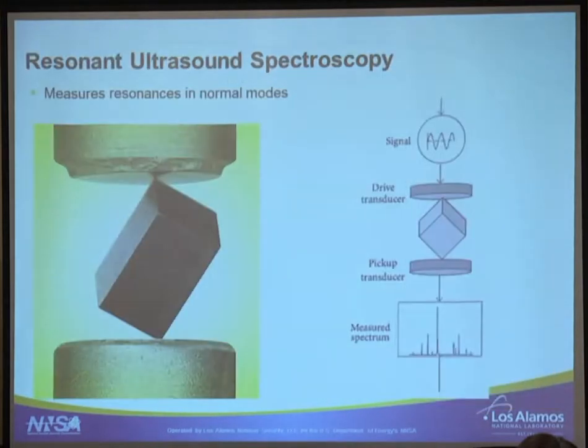I know. Anyway, so the basic technique is actually really basic, and that's the beauty of this technique, and very simple. So you have basically 2 transducers, piezoelectric. In one you put an excitation, a signal that you're going to be sweeping in frequency, and the other picks up. And that's it. That's all you're expecting. Very simple. And when you hit a resonance, a mode, a resonance of your sample, you see a peak.